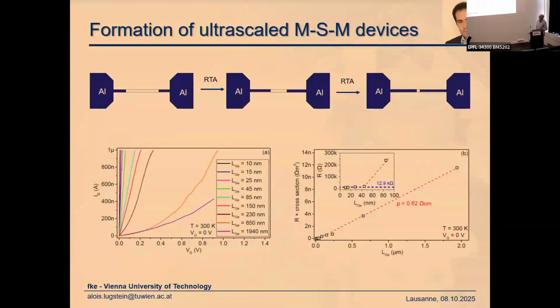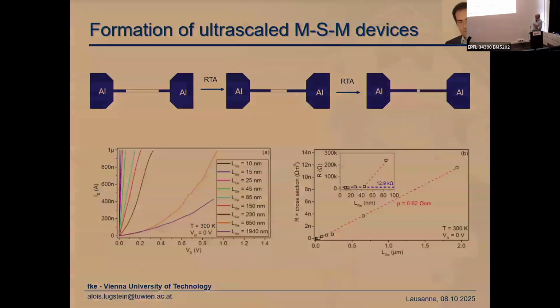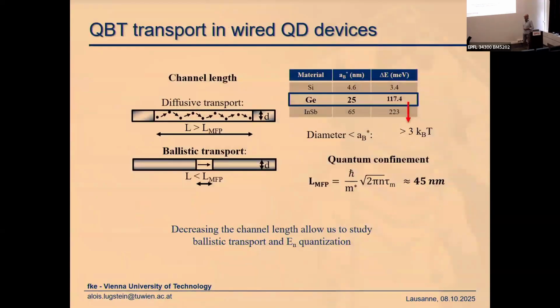What you expect, according to Ohm's law, is that it is directly dependent on the length. However, if you get shorter than 45, 50 nanometer, you see there's no longer any dependency on the segment length. And the reason for that is that the mean free path of electrons in germanium is about 45 nanometers. So we definitely enter the regime where we have ballistic transport even at room temperature.